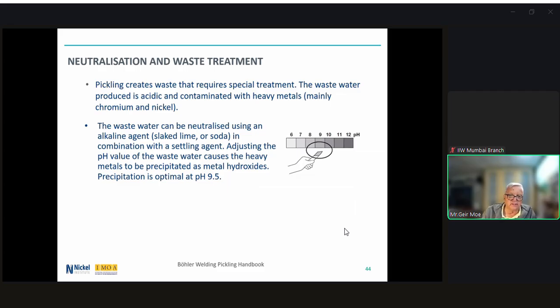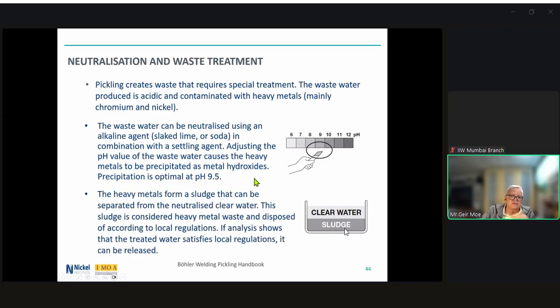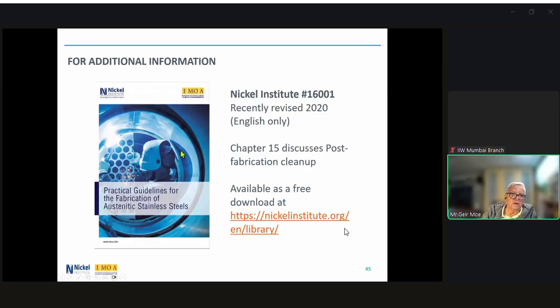agent. Adjusting the pH value of the wastewater causes the heavy metals to precipitate as metal hydroxides, which precipitation is optimal at about a pH of 9.5. These heavy metals then would form a sludge that can be separated from the neutralized clear water. This sludge is considered a heavy metal waste and should be disposed of according to local regulations. If analysis shows that the treated water satisfies local regulations, it could be released.